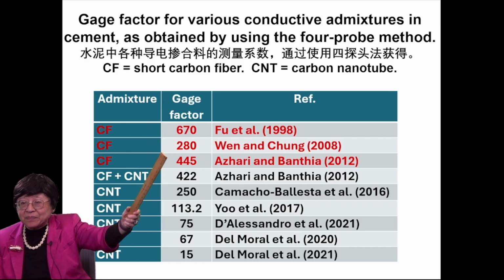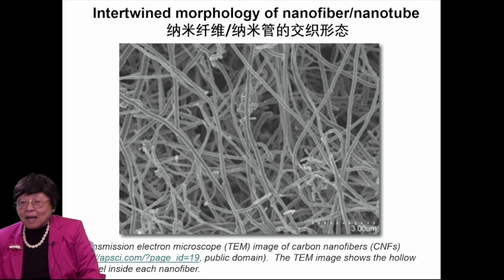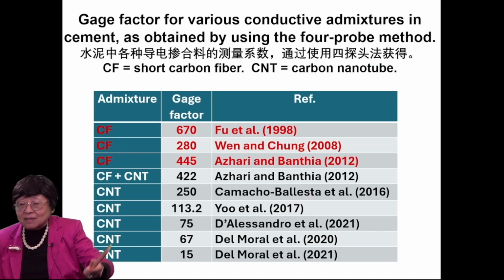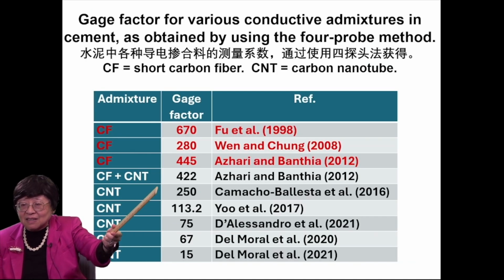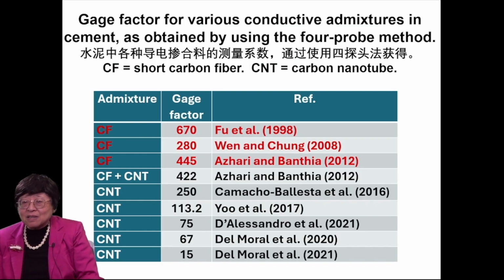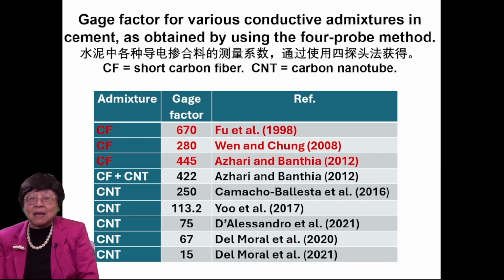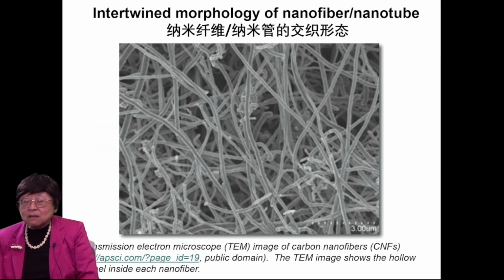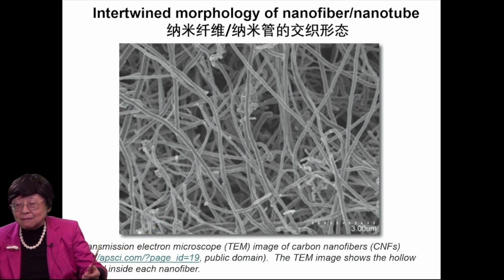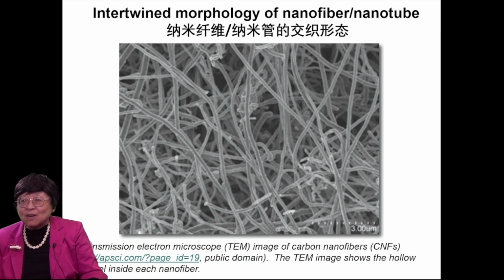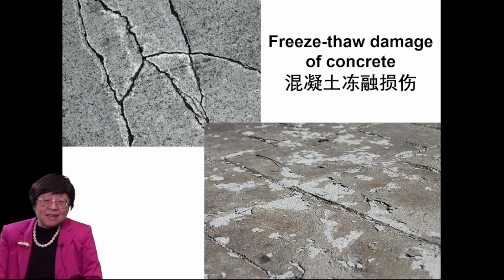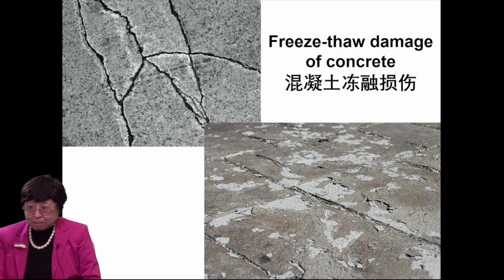all pretty high. Okay, and so CNT alone is not so great in the gauge factor. So using the CF in the absence of CNT is most effective in giving the highest gauge factor. The reason why the CNT is not so helpful is the intertwined morphology. So, you know, it's not individual CNTs or nanofibers, they're clumped together, and that's why they are not so effective.